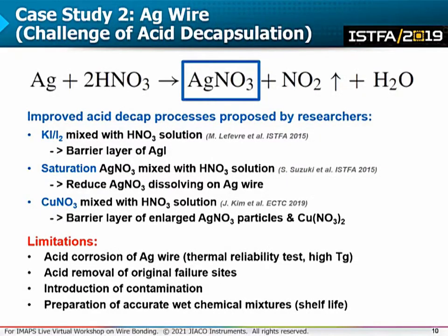On the next slide, I will talk about acid decapsulation of packages with silver wires. Silver-based materials are inherently susceptible to etching damage by acid. For that reason, some of the following methods have been proposed to improve conventional acid decapsulation. Two out of these three presented methods provide a barrier layer, which will protect the silver surface from being damaged in acid.